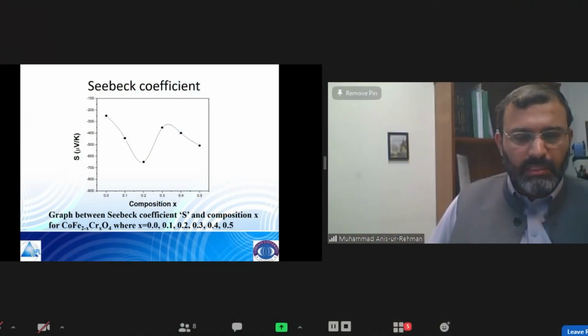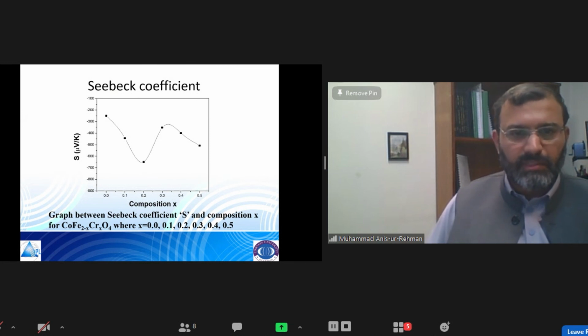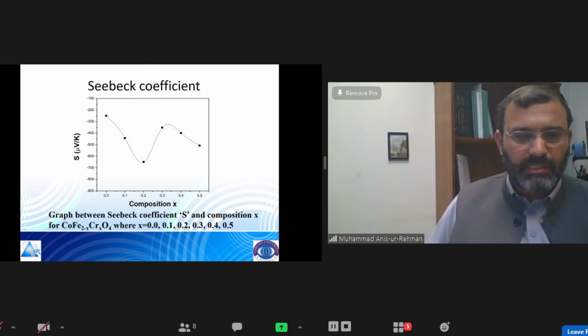The conduction in these materials is quite problematic and difficult to explain, so we are trying to find out what the mechanism actually is. We have submitted a project at the EXAFS beamline. Maybe if we get the time, then we can define how the conductivity is controlled by the local structure of the ions within the material. So maybe then we can clearly define what the reasons are for this specific trend. Okay, thank you very much again.